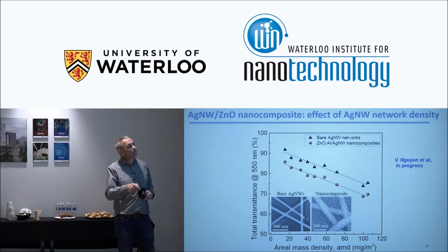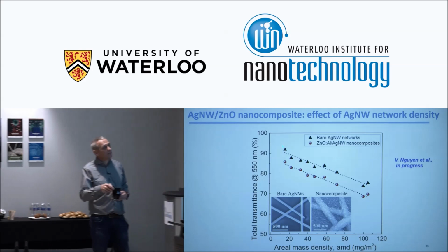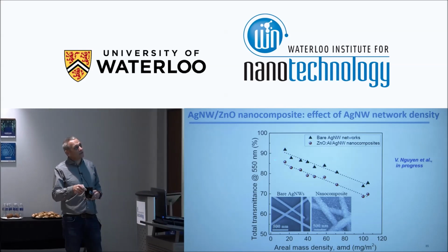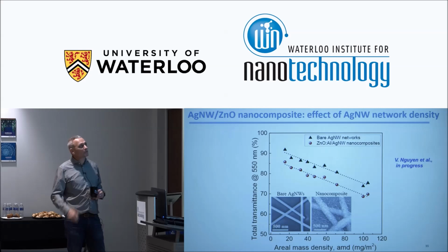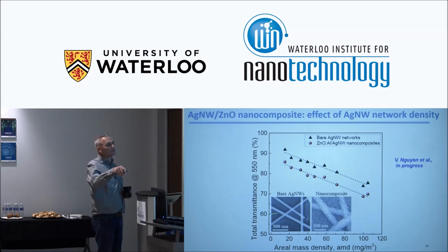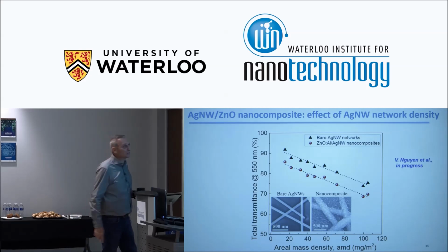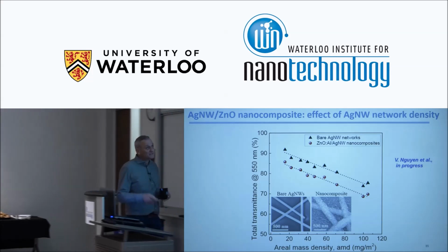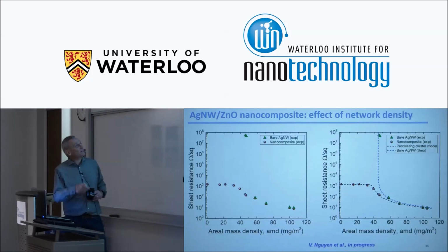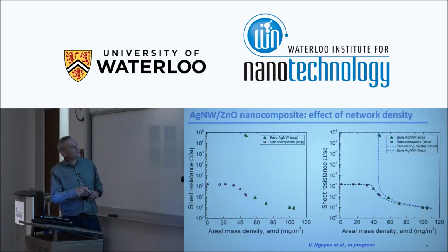For example, see the total transmittance versus the areal density. For bare nanowires and zinc oxide, we can see that when we are putting more nanowires, for sure, we are less transparent, and when we are putting zinc oxide, there is a decrease of transparency. And you can see the SEM picture here for the bare nanowires and for the nanocomposite. But the point as well is these electrical properties: the sheet resistance in log scale versus areal density. For bare nanowires, that's in green.